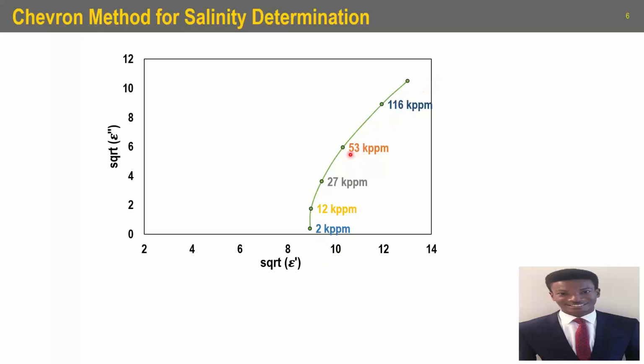curve. Then what they go ahead to do is that they make measurements on Berea samples with different porosity and saturations, and that have been imbibed in these particular concentrations. And from there, based on the various measurements on the Berea samples, they can extrapolate to the calibration line to determine what is the saturation, as shown in this chart, for the various samples imbibed in different concentrations of brine.